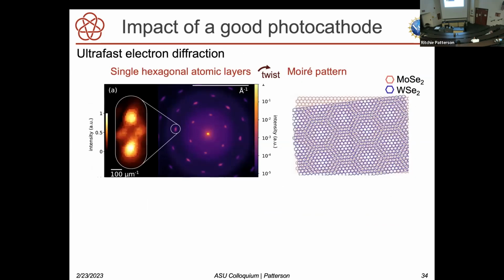I thought I'd show you something with the impact of a good photocathode. This is one that has MTE that's around, I think, 60 millielectron volts. And this is an ultra-fast electron diffraction pattern. Here, what we've taken is two hexagonal atomic layers and then given them a little twist, so that there's both the small scale hexagonal structure, but also a large scale one that comes out, the moire pattern. And if you look at the diffraction pattern from that, you look at one of these bright spots, it actually consists of two bright spots. One of those is from each of these two layers, but there are also two little satellite spots, and those come from the very large scale pattern.